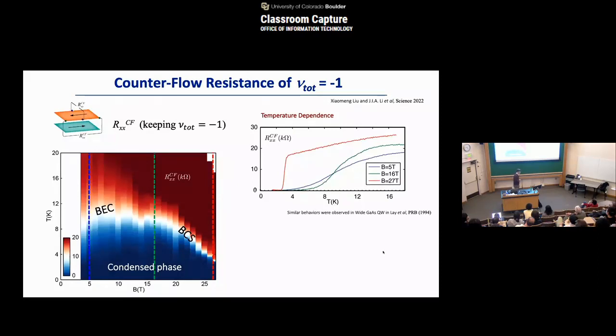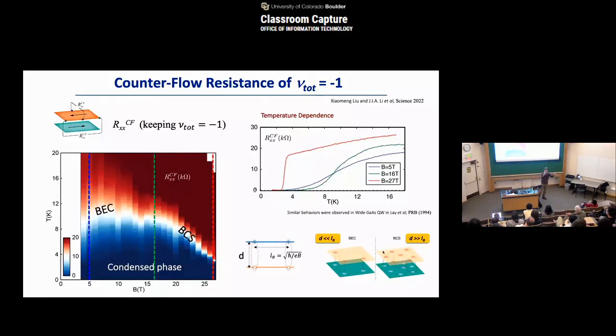Here the transition is almost like a BEC type of transition, which is expected because the distance between the magnetic excitons is tuned by the magnetic field. Here, basically, the distance between the excitons is large compared with the layer separation. Here, the distance between the excitons is really close, and there you drive more toward the BCS type of regime. So in a sense, this is a nice way to demonstrate that the phase boundary can be mapped out in this type of system, right?